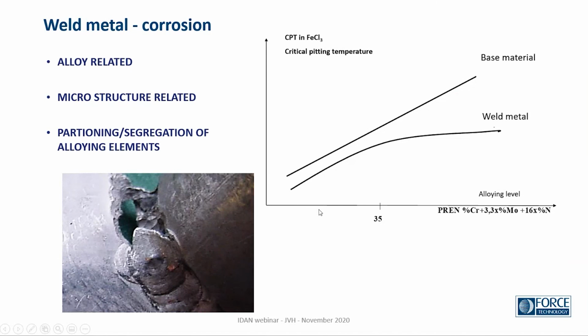For higher alloyed materials like stainless steel, we could define a relative factor for their corrosion resistance, and it is defined in a lab testing environment called ferric chloride. And in a logarithmic diagram, we could get a straight line for the relation between the alloying and the temperature where it fails, the critical pitting temperature, by using this formula, where we have chromium plus 3.3 times the molybdenum content plus 16 times the nitrogen content.